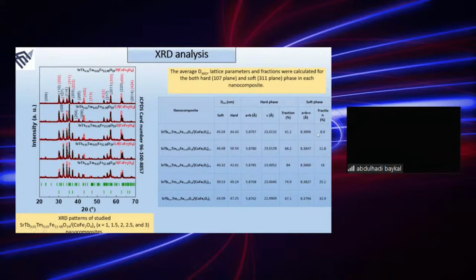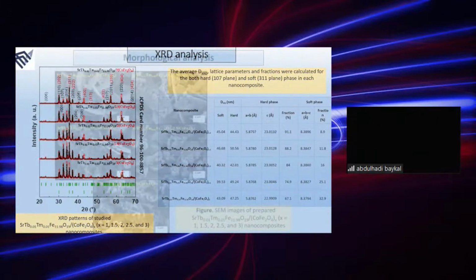You see, for example, when x is equal to 1, which is given on the first line, the fraction of the hexaferrite part is 91.1, and the fraction of the spinel part is about 9. When you add this column and this column, for all nanocomposites, you will reach 100. Okay, that is the crystal structure information that we can deduce at the end of our Rietveld phase analysis. And then another thing that we did, as I told you before, is the morphological analysis.